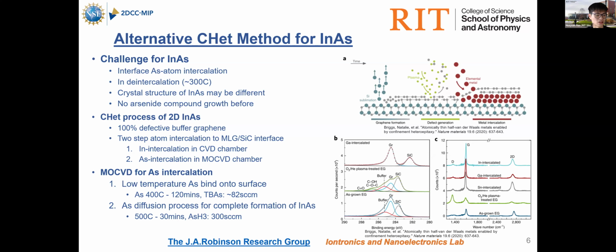And the second step also occurs at a higher temperature, and that's why we use a different precursor that decomposes at a higher temperature. So in this process, after we bombard the arsenic onto the substrate, in order to fully convert the arsenic near the intercalated edge, we have this high temperature process to diffuse the arsenic atoms and have a full conversion into indium arsenide.